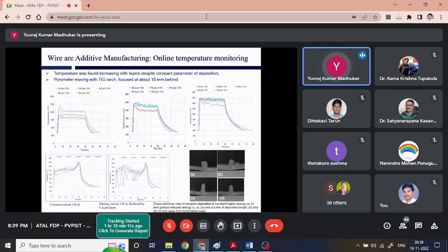When the number of layers increases from the 5th layer to the 15th layer, despite keeping the input energy constant, the peak temperature is increasing. However, it has been observed that when we deposited further layers beyond the 15th layer, it becomes almost constant. It is not increasing beyond that because our input energy has a certain limitation as well. So certainly we can consider temperature as the parameter which can be controlled to regulate the input energy at a desired set point temperature, depending on the material we are dealing with.